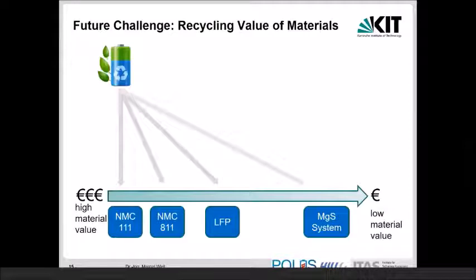But already with NMC 811, that's not so nice from a recycling perspective, because only a low amount of cobalt is in such a cell. And with LFP, there's no cobalt. Then, of course, from a recycling perspective, it's not so interesting, especially the black mass. Maybe the aluminum and the housing are interesting, but not the black mass. And if you think about the magnesium-sulfur system, the value is even lower. And then you have to think about how you can recycle such a system with such low value of the materials.